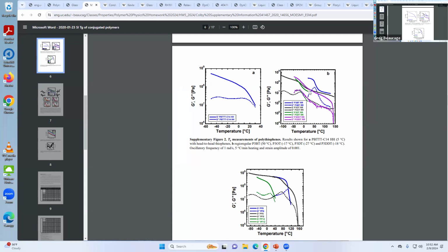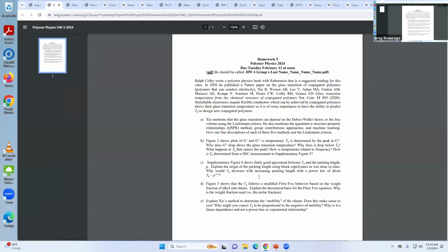So anyway, if you raise the plateau modulus, that's going to shift the center of the sigmoidal over to the left. Like if you keep the solid part the same, and then the rubbery part. So this is a glass, like a glass marble, and then this is a rubber. If you lift the rubber part and keep the glass the same, which is no reason the glass would change, then that center point would shift to the left, and you lower the Tg. So that's why the plateau modulus might be associated with shifts in the Tg. Right, from the perspective of this measurement. So anyway, if you look at it carefully or just kind of probe into this thing, there's a lot of things you could think about here.